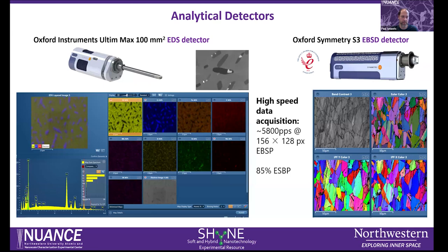From the EDS mapping, we basically reveal that these grains are chromium inclusions in a nickel matrix, and these small precipitates here appear to be niobium. An example of such a structure can be found over here, with the niobium shown in red and the chromium in blue.